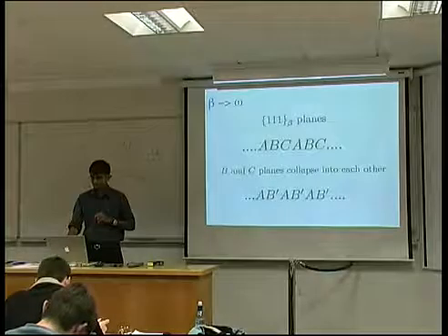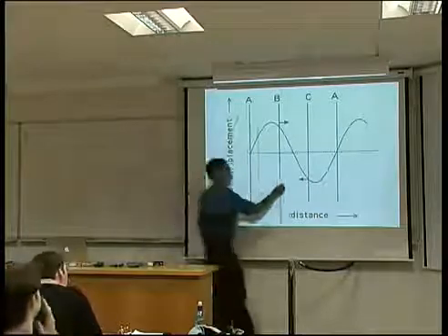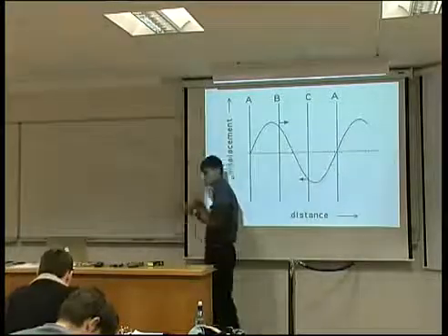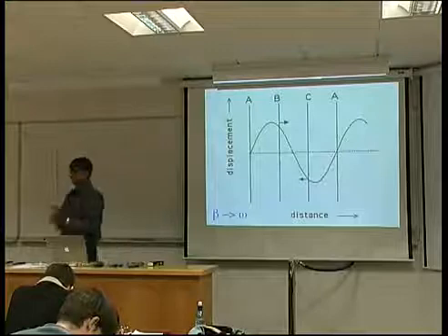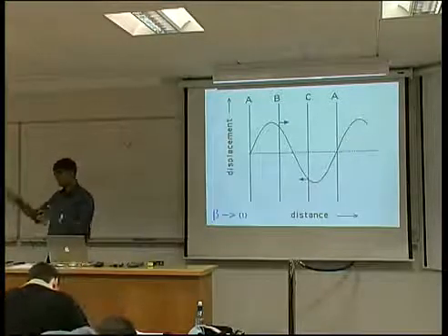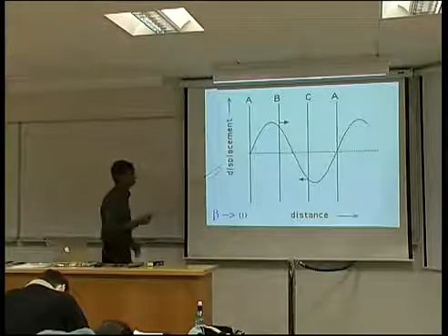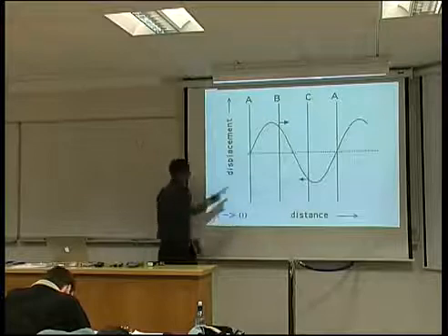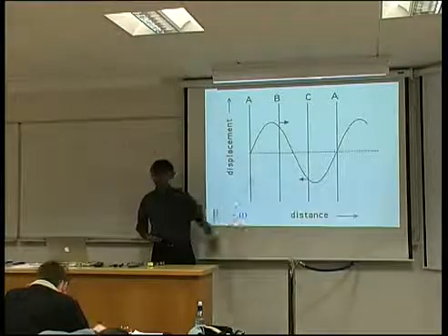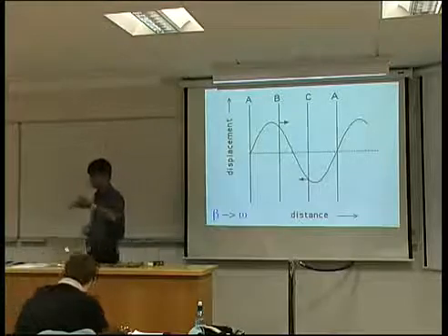Right. So look, we have these planes of atoms, which are the 1-1-1 planes, and they're stacked in a repeat sequence A, B, C, A, B, C, and they all have the same numbers of atoms per unit area. Okay? Now imagine that I pass a displacement wave through the system, okay, where this represents the magnitude of the displacement. Okay?